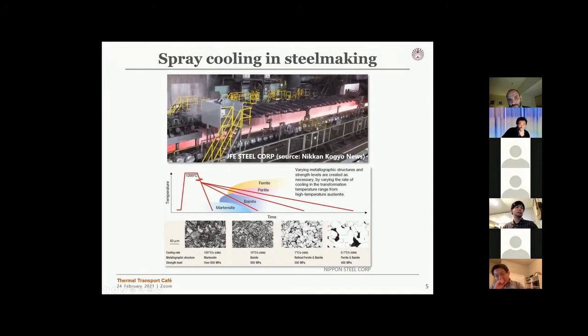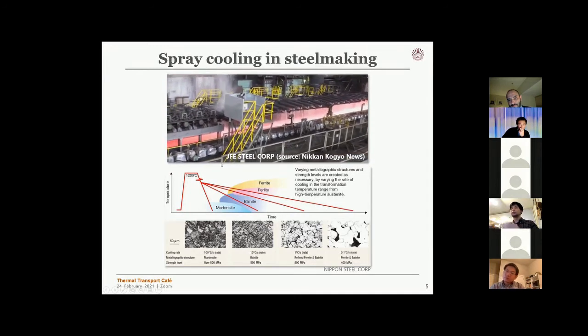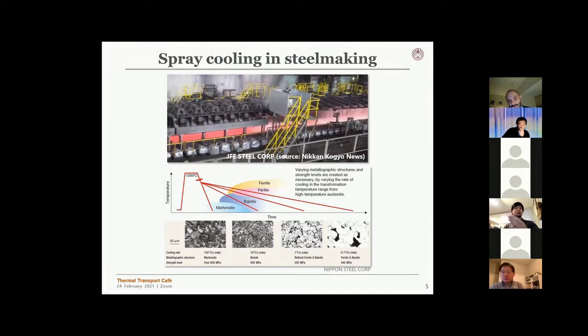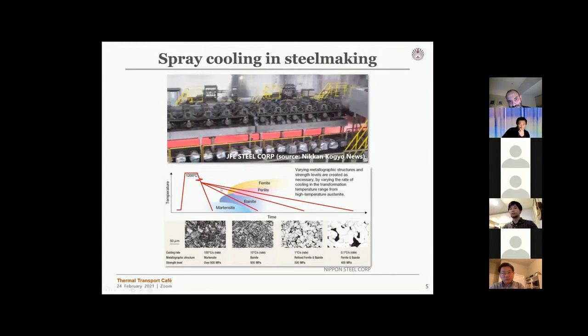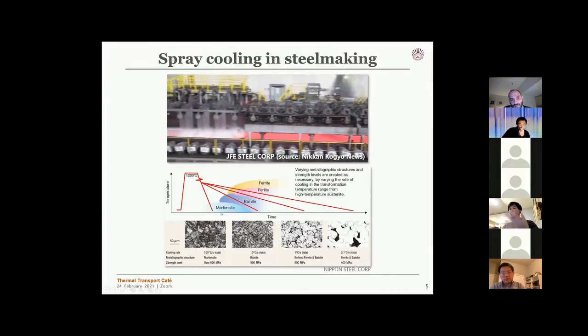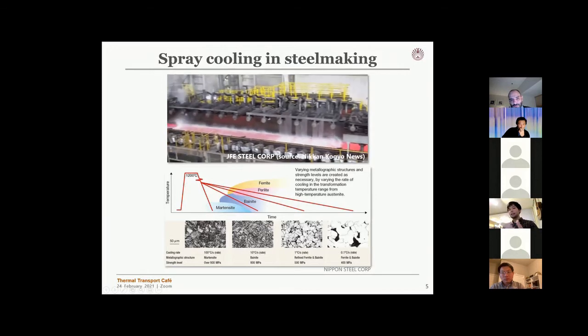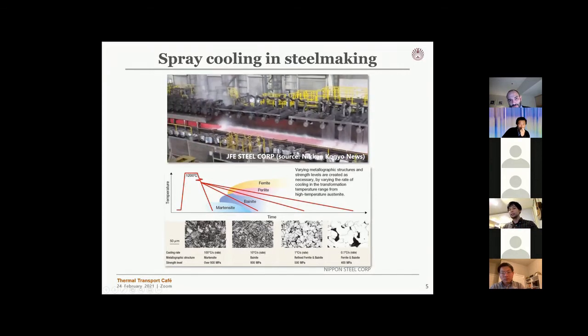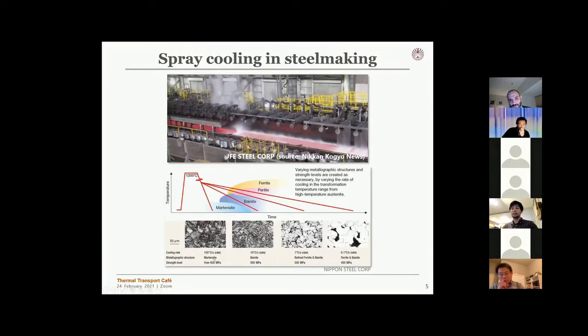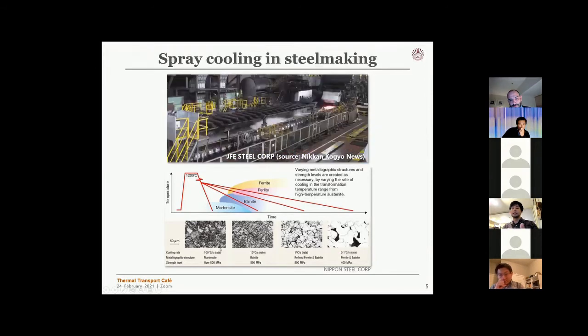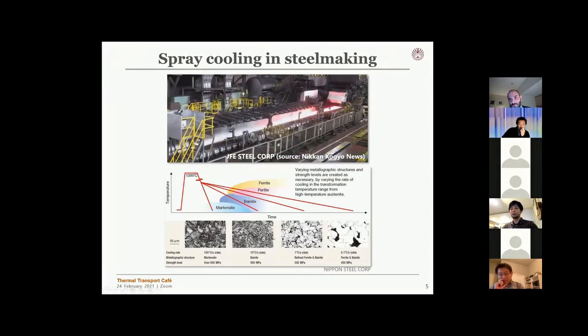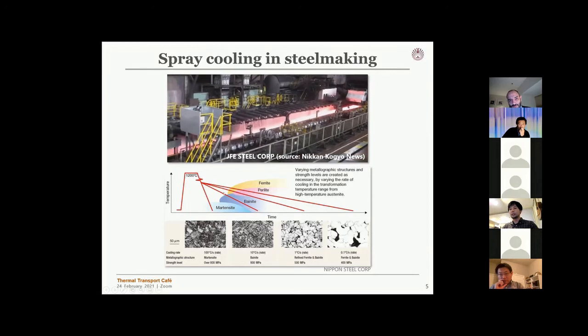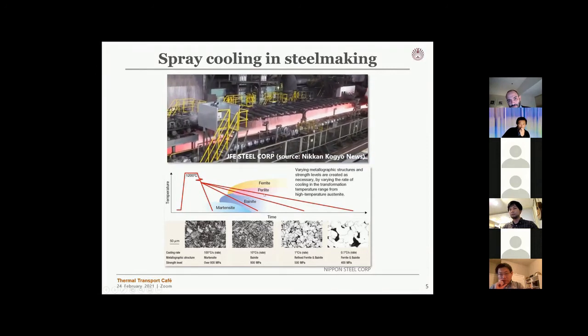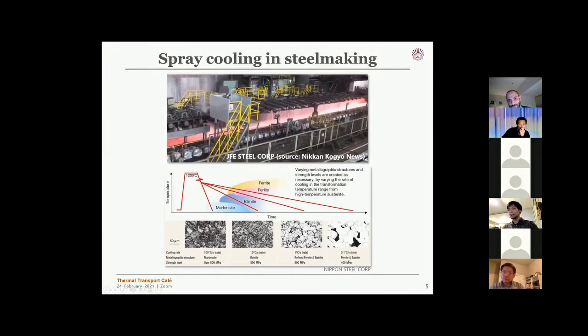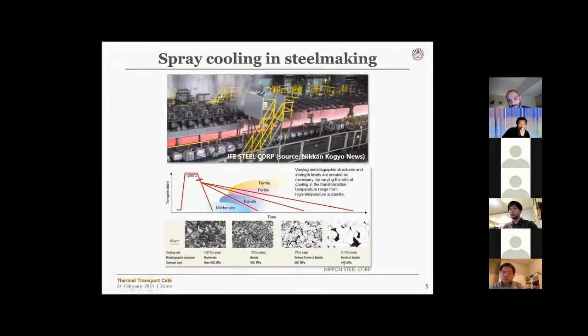Why we do this is we want to control the thermal history of the plate, so that we can create some microstructures within the material, which basically changes the strength of the material. So if you change the cooling profile, you have different microstructures, and you have a desired strength level.